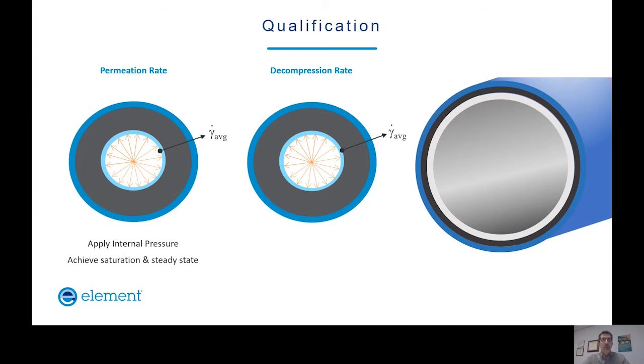So once we achieve that steady state of permeation, we look at what happens when we rapidly decompress the product. And is there a limit to what that decompression rate can be? And that's established through a series of tests that bump right up to the onset of blistering or potentially collapse of the product. And by collapse of the product, I don't necessarily mean the entire product. When we talk about collapse, it can happen in any one of the layers of the product.